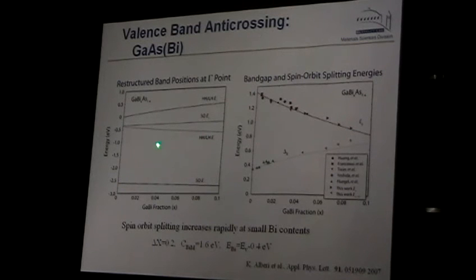And the spin orbit splitting, which in gallium arsenide is about, in this case it's about 0.4. The spin orbit is 0.35, yeah, but it's measured from here. So spin orbit splitting goes very rapidly. It's already 0.8 for 8% Bi content. So this is something which could potentially have some application.